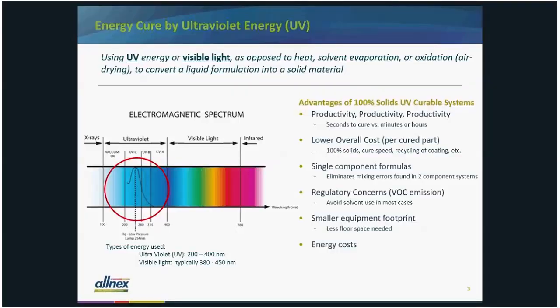So I mentioned we're going to start with a little bit on ultraviolet curing. And when we say UV curing, we're talking about using UV energy or visible light to cure our films. This is opposed to using heat or solvent evaporation or oxidation, otherwise known as air drying, to convert your liquid film into a solid coating. And to do that, we use energy of the electromagnetic spectrum between, say, 200 and 400 nanometers, maybe into the visible up to 450 nanometers, as indicated by the red circle on the chart on the left.